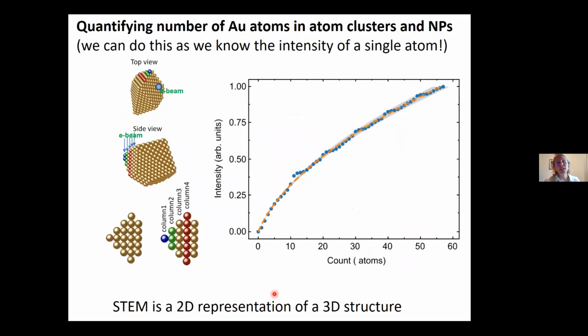The other thing I want to point out, and I think is really neat, is that if you can measure the intensity of a single atom, you can start to count exactly how many atoms are in any of the 3-dimensional structures you see. When you're imaging with this very high resolution electron beam, you're actually imaging through columns. If you know the intensity of a single atom, you measure the intensity of each of these atom columns and report that as a spot. We can calibrate this and pull out from intensity maps, which is what you're seeing, how many atoms are in there. So we can now convert all of our 2D images into a 3-dimensional representation, which I think is really neat. The only other way to do that sort of thing in TEM is using tomography techniques, and I'm not sure whether they can get to single atom or not. I'm not sure on that.